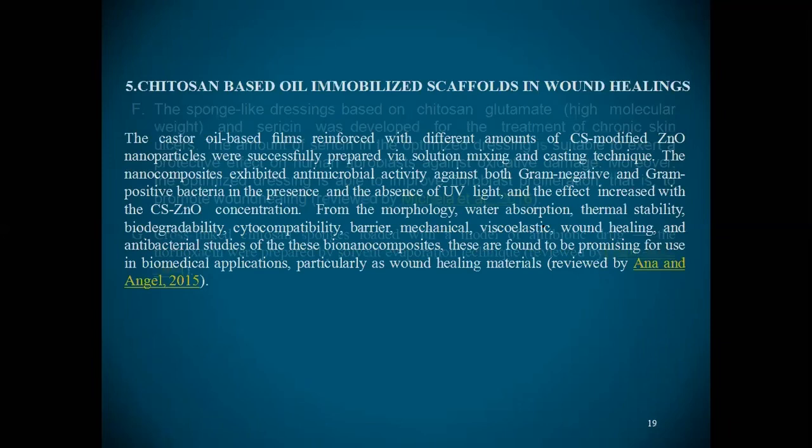The chitosan based oil immobilized scaffolds in wound healing. The castor oil and chitosan modified with zinc oxide nanoparticles. Chitosan can be made into a film. This prepared film is effective in antimicrobial activity against both gram-negative and gram-positive bacteria. It depends upon the concentration gradients.